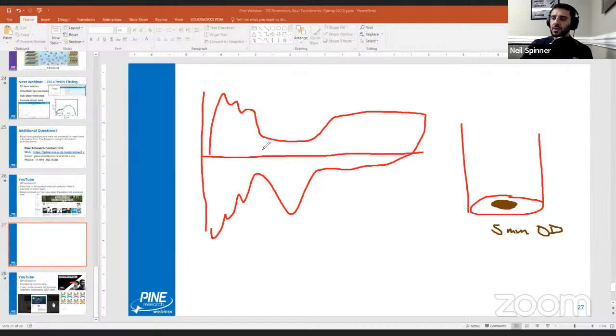The platinum CV is very interesting because there are all these features. This right here is platinum hydrogen desorption. This down here is platinum hydrogen adsorption. This is basically platinum oxide reduction, or oxygen reduction if there's oxygen, but usually you're doing this in neutral-ish conditions, so this is just oxides on the platinum. This is the platinum oxide formation, or sometimes hydroxides. There's variations in what these are called, but basically something like this. What is done is really pretty simple, actually. The only place in the platinum CV where basically nothing is happening is right here.